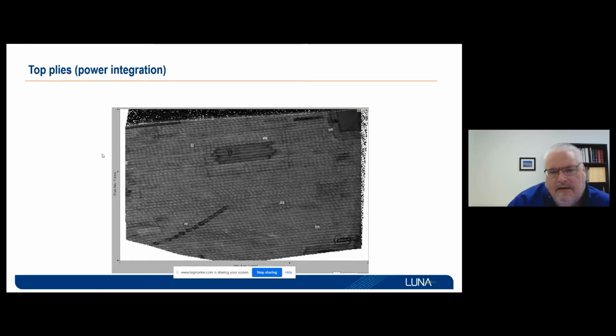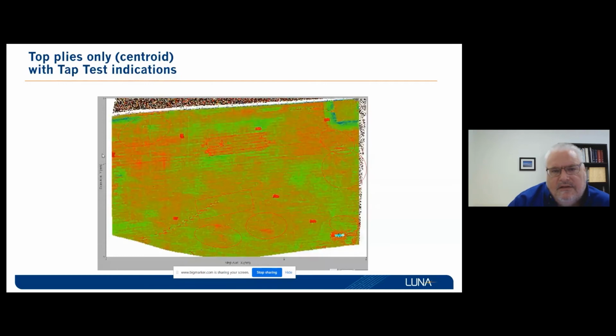Here's just another image that we've done with handheld imagers painted together of, let's say, top plies of a radome panel. And then this is some indications where the tap test showed flaws. So oftentimes with radomes, you simply tap and listen for the sound to see if delamination has occurred.